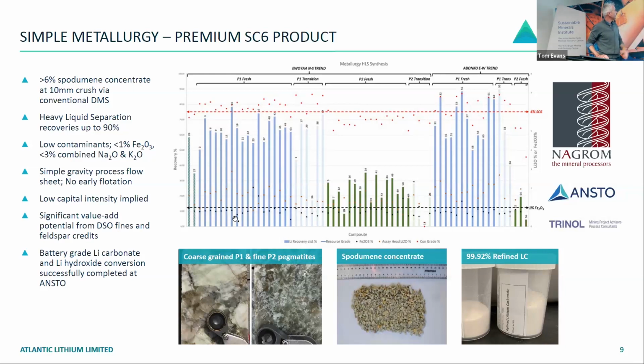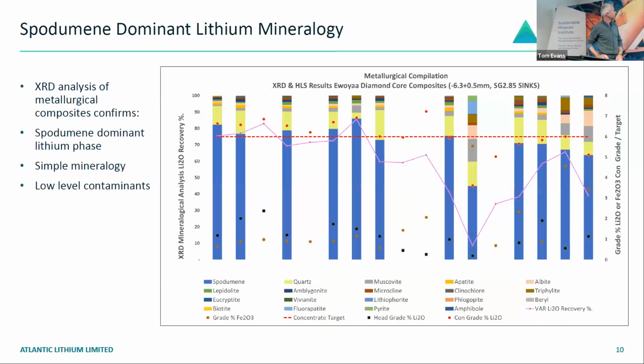So we're able to produce a high grade spodumene SC6 concentrate, and we've also demonstrated that we can convert that to hydroxide and carbonate, which was done here at ANSTO, but that's not really our focus. We're about producing a spodumene concentrate, and we're able to produce this concentrate through a simple DMS-only process flow sheet without having to go to flotation.